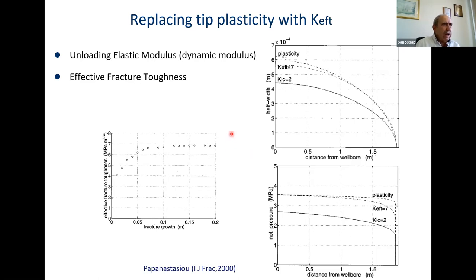What I will advise for the practitioners is to use the unloading elastic modulus in the classical hydraulic fracture simulators. The reason for using the unloading elastic modulus is because near the fracture tip, we have plasticity, but once the fracture propagates, behind it unloads elastically. So the bulk of the area is under unloading mode.